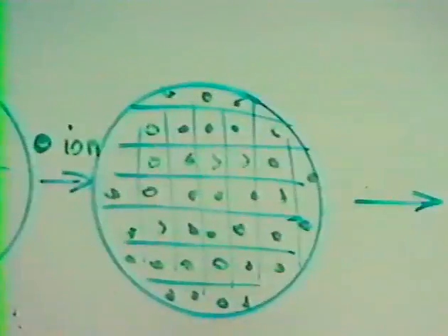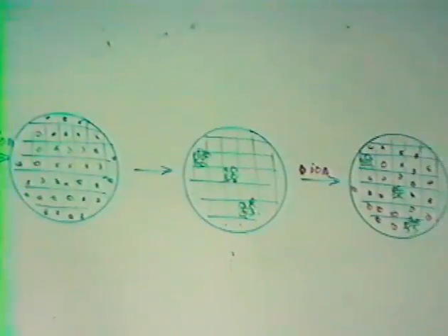I think the size can be increased just a little bit. This is indicated by the xenon adsorption measurement, and the bimetallic formation is indicated by XAFS, and the change, the surface coverage by silver atom is indicated by xenon NMR. The chemical shift decreases in the xenon NMR.